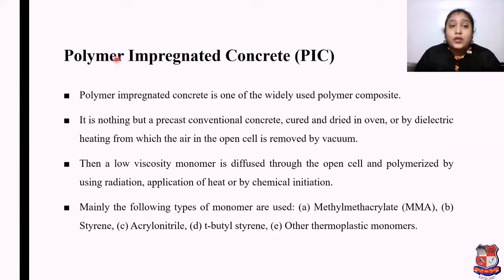Now, if we talk about polymer impregnated concrete, PIC, then polymer impregnated concrete is one of the widely used polymer composites. It is nothing but precast conventional concrete cured and dried in an oven or by dielectric heating, from which the air in the open cells is removed by vacuum. Then a low viscosity monomer is diffused through the open cells and polymerized by using radiation, application of heat or chemical initiation. Mainly the following types of monomers are used: methyl methacrylate, styrene, acrylonitrile, t-butyl styrene, and other thermoplastic monomers.